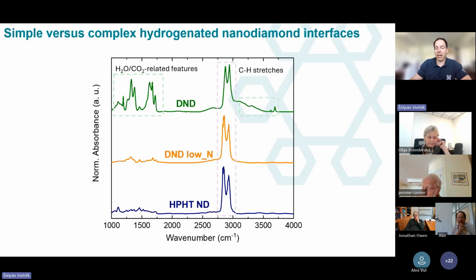Okay, so this is, I think, the CH on nicely hydrogenated diamond. So this is maybe the reason or the driving force for this transfer doping, charge transfer whatsoever. But still, we see the coexistence of these sp2 features, like we see from the Raman. So that's probably the uniqueness of this HPHT nanodiamond, and it explains the conductivity because of this nice hydrogenation, and the positive zeta potential at the same time because of this sp2 carbon. That's my view.